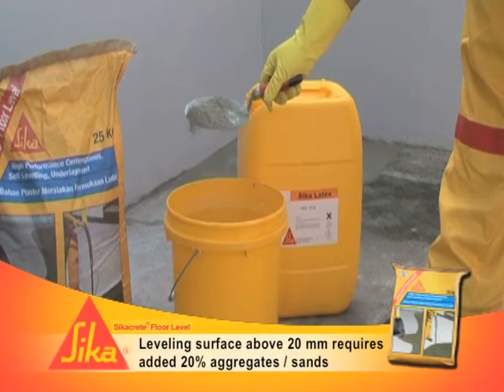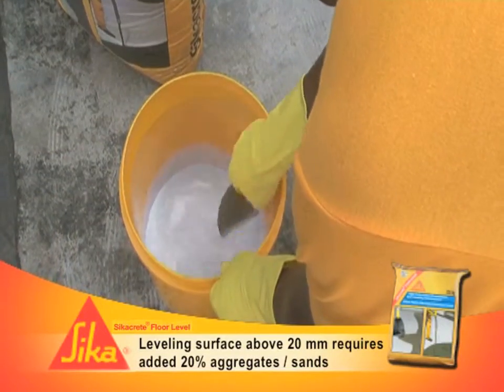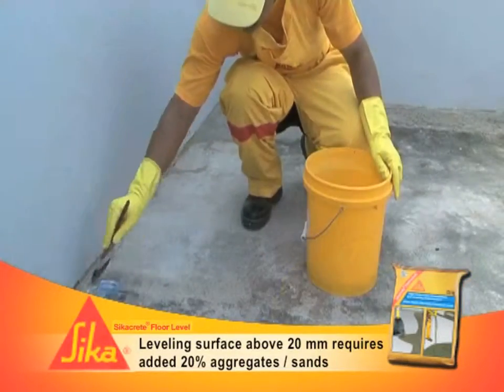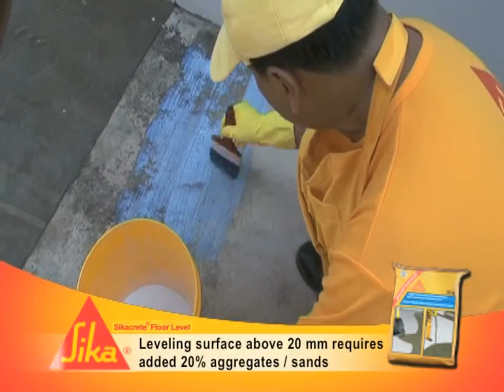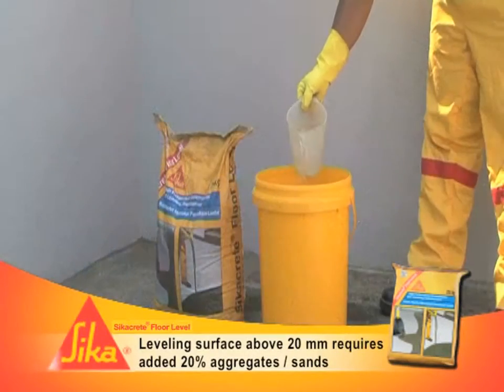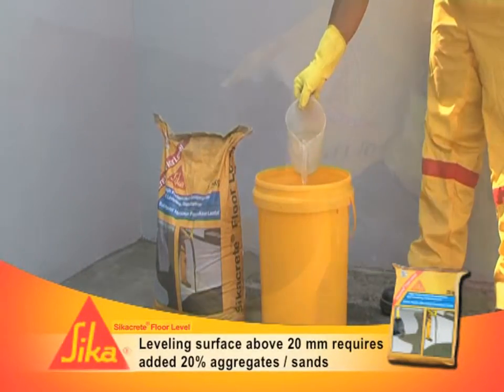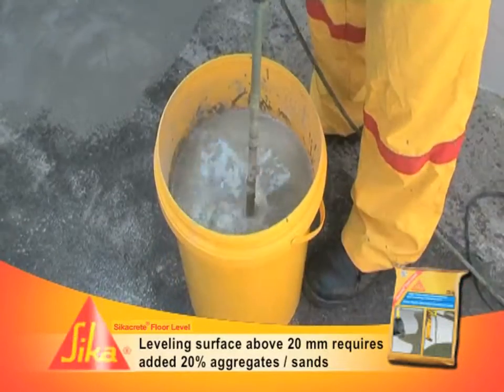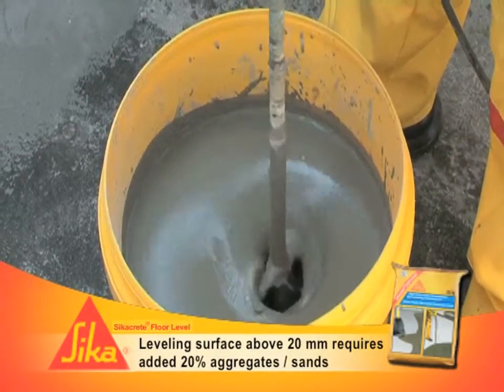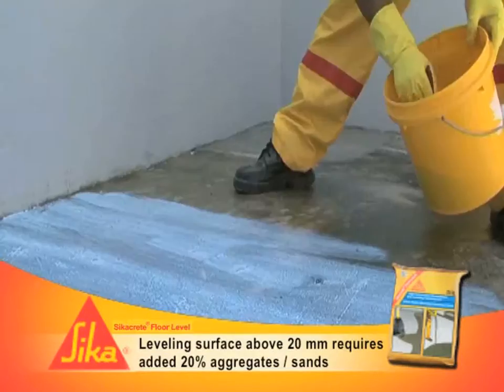The surface must be sound, damp, and clean. Prime with Sika Latex or Sika Top 77D with cement equal to 1:1 to improve bonding to the substrate. Mix one bag of Sikacrete floor level with 3.5 to 4.5 liters of water.